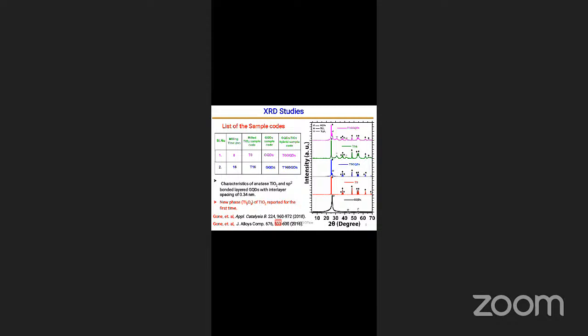One is T0, where T0 means milling time, so T0 TiO2 is 0 milling time, and the T0 GQD is the hybrid, the T0 sample with GQD. Next, we have done ball milling for different time intervals like 4 hour, 8 hour, 12, 16, 20 like that. But we have chosen only the particular sample that is actually showing the best results. So that is T0 and T16 for comparison. These results are also available in the Journal of Alloys and Compounds.